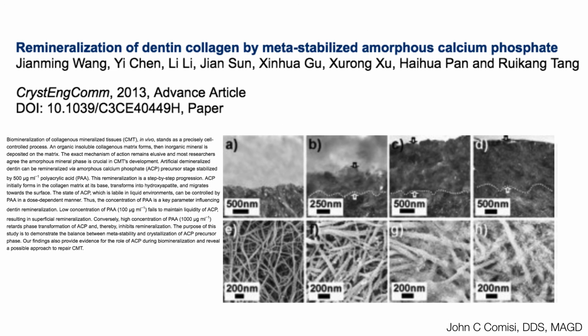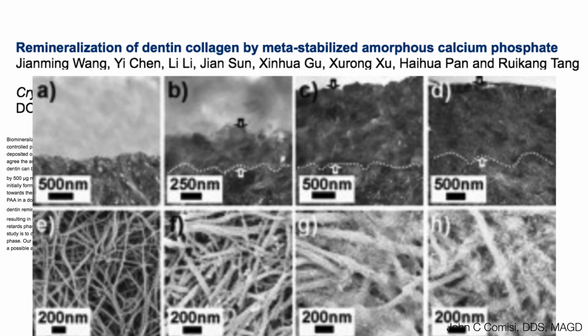This paper in CrystEngComm 2013, entitled Remineralization of dentin collagen by metastabilized amorphous calcium phosphate, shows step by step how in vivo collagen can be remineralized via the amorphous calcium phosphate. Note the growth and enhancement of the collagen fibers from image A on the left through image D on the right. Fascinating, isn't it?